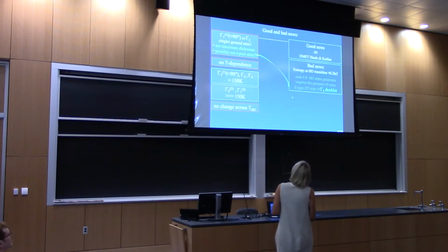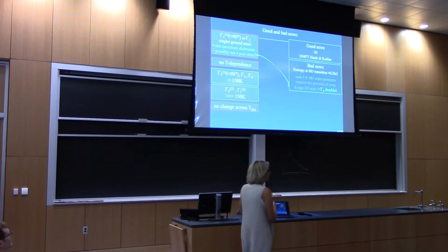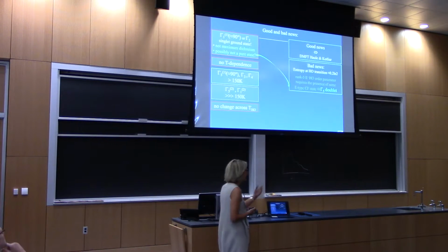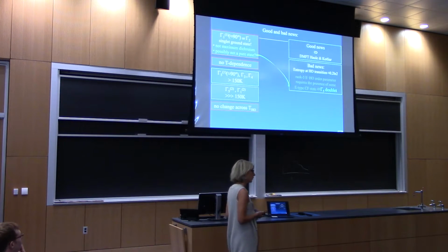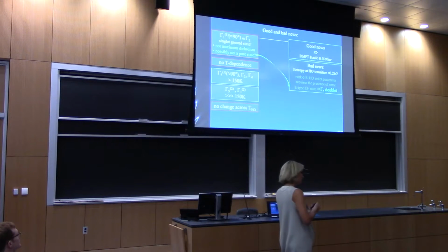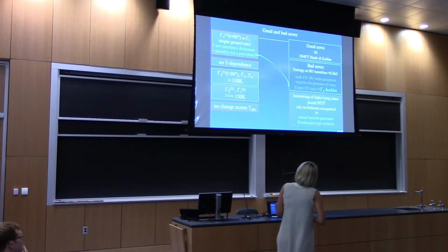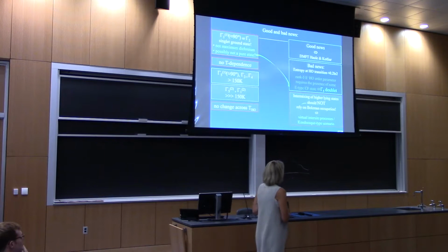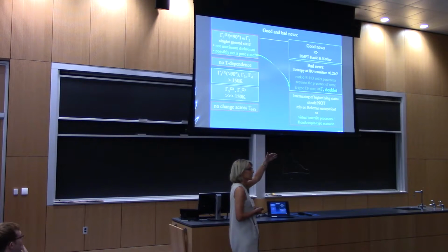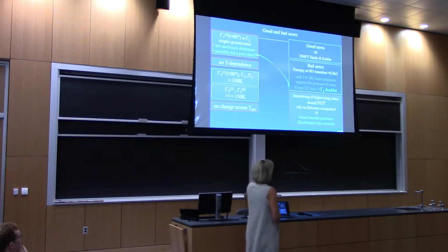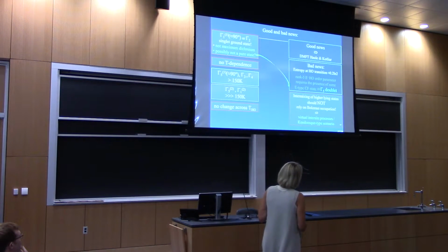And then we have to say, let me go back here. I said we did not observe the maximum possible dichroism from the simulation. That means there could possibly be another state contributing to the ground state, so that our ground state is a mixture of quantum states, if you like. But that cannot be by Boltzmann occupation, because I showed you from the absence of T-dependence that the next higher state must be at least 150 Kelvin above the ground state. So what one could imagine is that we have inter-site processes which mix in another state, or a Kondo-type scenario, and this is what I would like to show you.